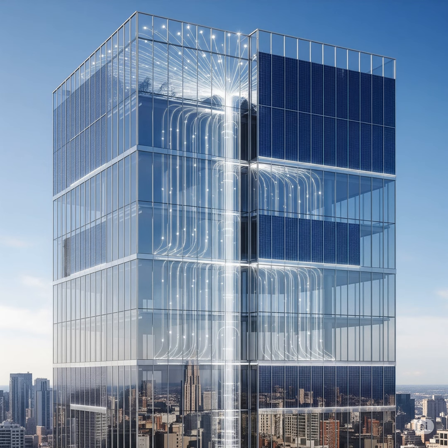They've got a really smart two-pronged approach. First, on the material science side, they've worked on making the perovskite itself more robust. They do this by doping it, basically adding tiny amounts of other atoms, like cesium and rubidium. Okay, strengthening the core material. Exactly. That gave them much higher thermal stability, and they reported hitting 20.8% efficiency with that doped material back in January 2019. That's impressive.